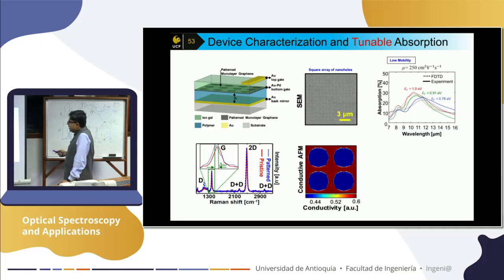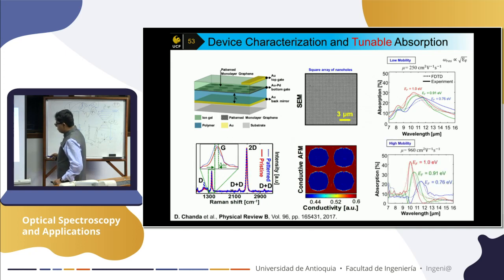So now when you apply a gate voltage, we can see that you can not only improve the absorption, that we started with measuring about 30% or so, to about 45%, but also you can create tunable absorption. Other materials don't allow you, like normal gold, or even a normal semiconductor, say indium antimonide or mercury cadmium telluride. It absorbs everything, cannot have this tunability. This is a special property of graphene, where you can change the Fermi level and change the carrier concentration such a way that you can tune these absorption bands.